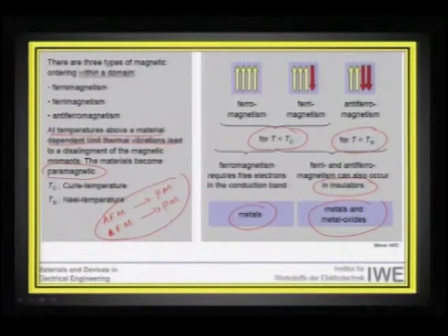But when you try to disturb this manganese-oxygen-manganese alignment by substituting strontium for lanthanum, you can actually bring about a collinear ferromagnetism, where you introduce a ferromagnetic exchange between neighboring manganese via oxygen 2p. Therefore, a radically antiferromagnetic insulator is transformed into a ferromagnetic metal, which is a very astonishing phenomenon in the case of oxides. So, most metal oxides are antiferromagnetic, but you can easily translate them into ferromagnetic oxides and thereby affect the conductivity by mere chemistry, and that is the speciality of materials chemistry in these oxides.